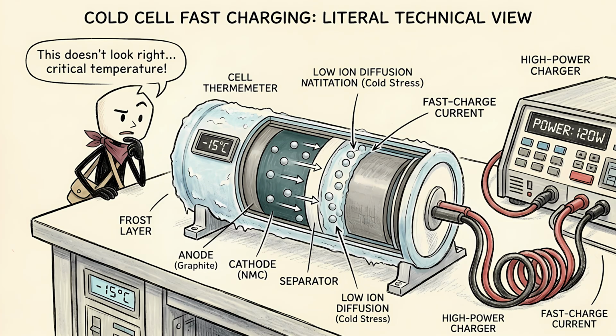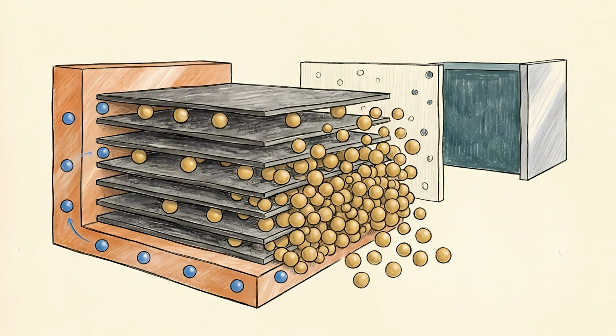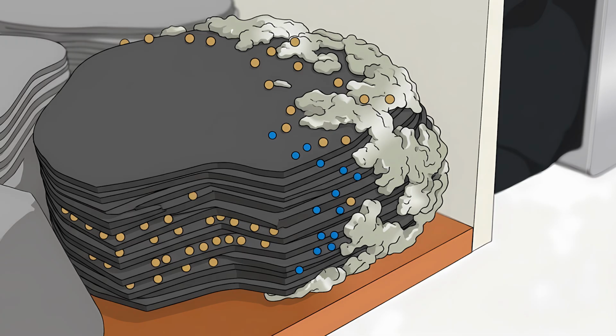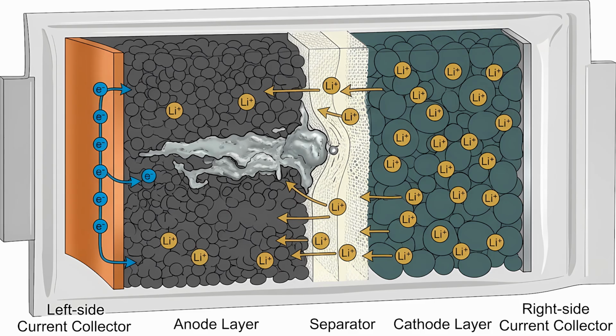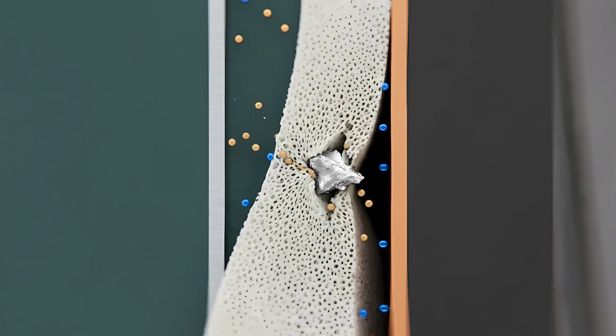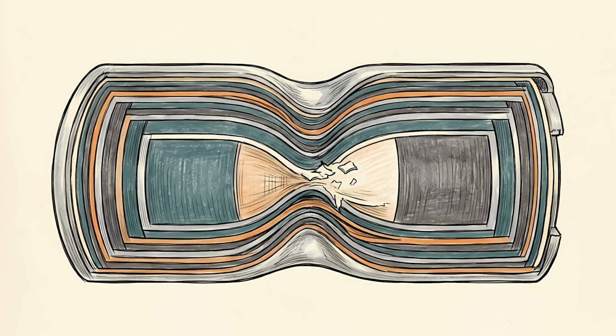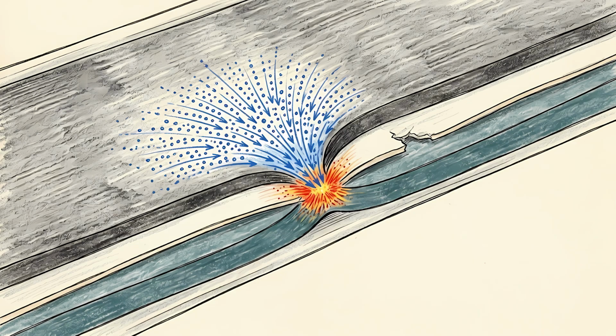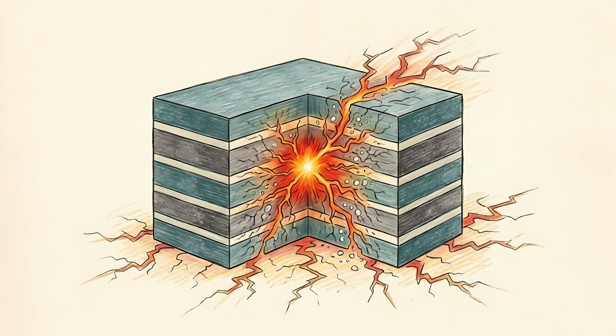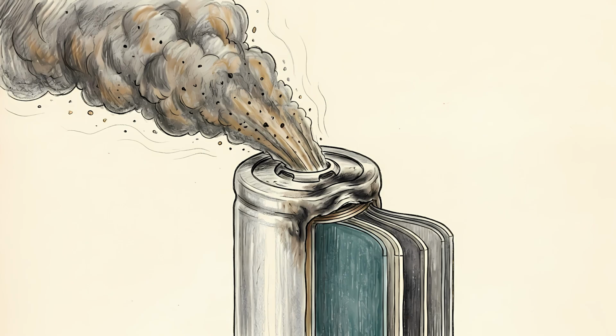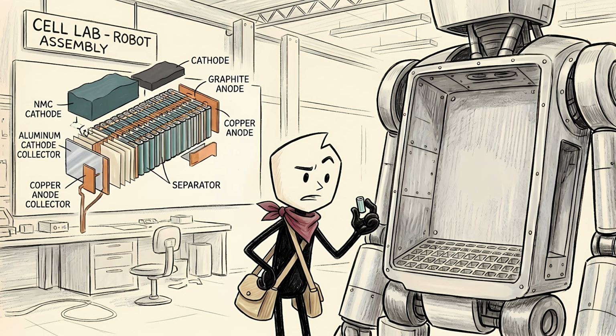During unfavorable fast charging, especially when cold or nearly full, lithium may plate as metal on the graphite instead of entering its layers. That reduces performance and can create safety problems. Contamination, damage, overheating, or separator failure can create an internal short circuit. The rapid heating can trigger further heat-releasing reactions, and in severe cases, thermal runaway. That is why a real battery needs more than cells.